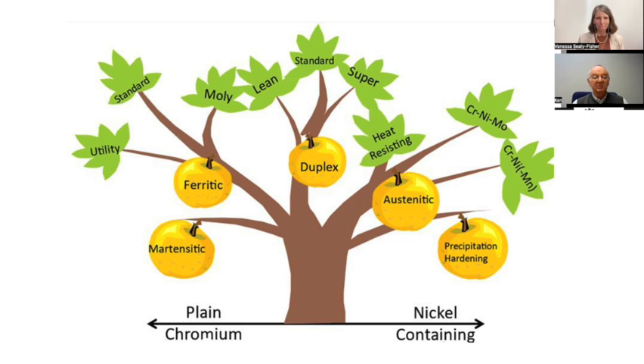We move on then to the ferritic branch, which again are so called because of their microstructure. They have a certain structure to the grains, and hence the term ferritic stainless steels. Again, they rely primarily on their chromium content for corrosion resistance. But the ferritic family have a very useful corrosion characteristic, and that is that they are immune to a form of corrosion known as stress corrosion cracking. That occurs in a chloride environment, so we refer to it as chloride stress corrosion cracking. Now, if there are chlorides present, there's also a risk of pitting corrosion taking place.